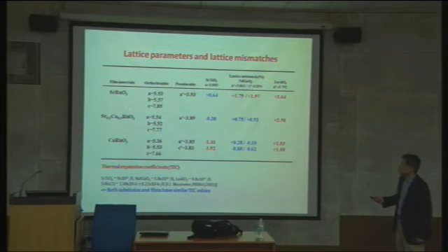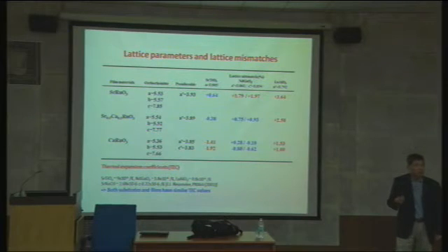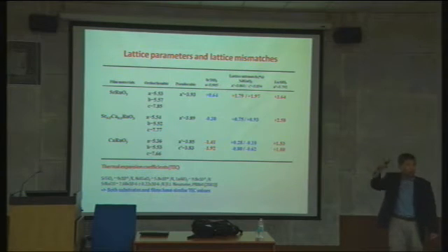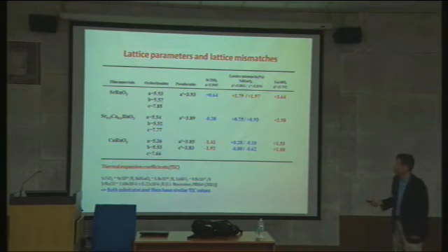But this is a completely solid solution. Pure strontium ruthenate, pure calcium ruthenate, complete solid solution. So when you alloy the system, the lattice parameter continuously increases or decreases, and in between, the value is somewhere in between. Then you use three different substrate materials: strontium titanate, neodymium gallate, and lanthanum aluminate, with large, small, and in-between lattice parameters. Then you can build a complete matrix of how the film grows, where it relaxes, and what the surface morphology is. You can visualize this epitaxy.